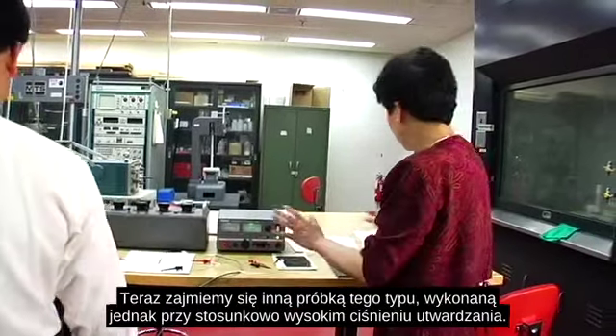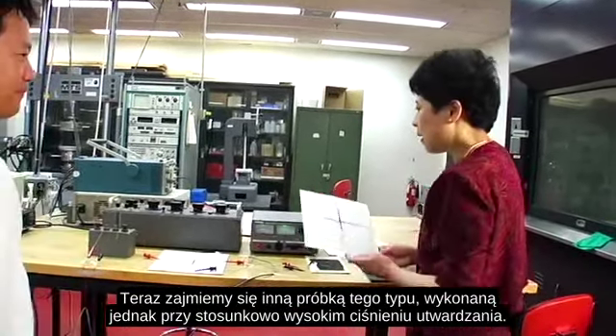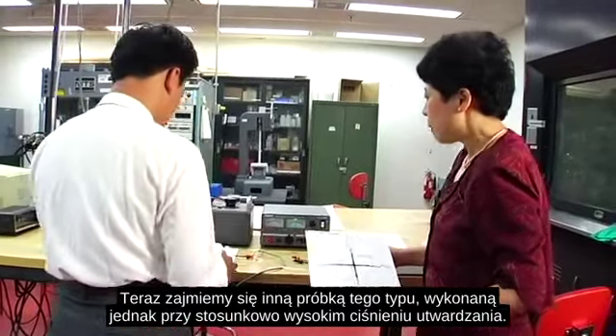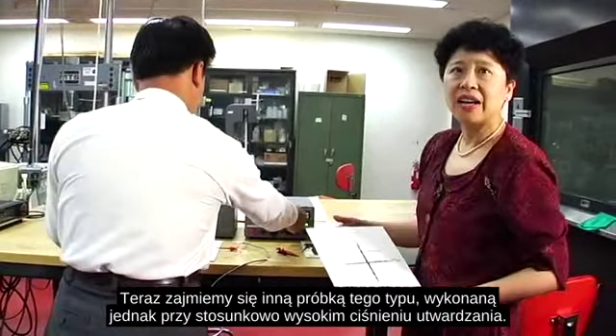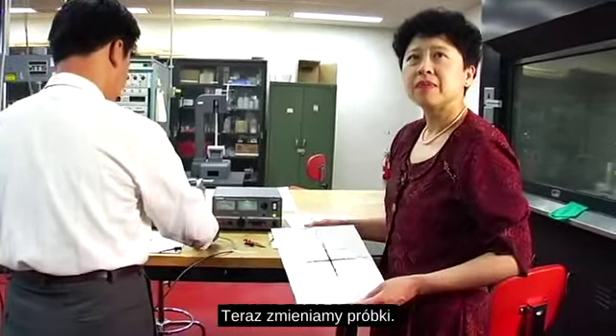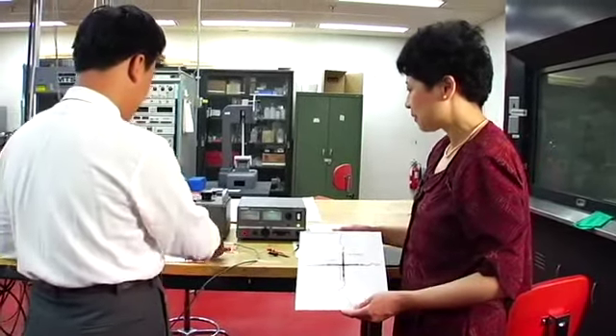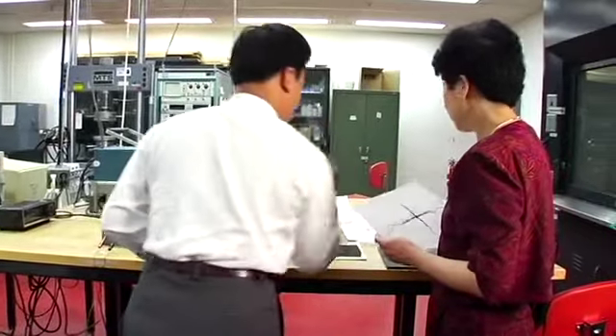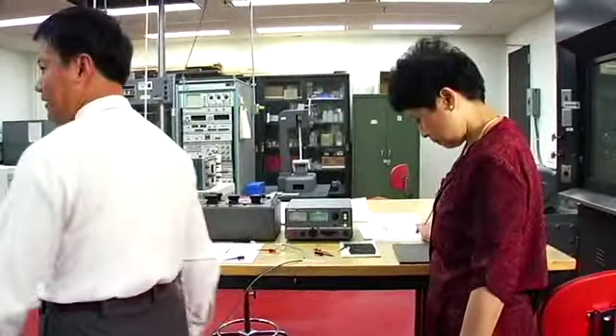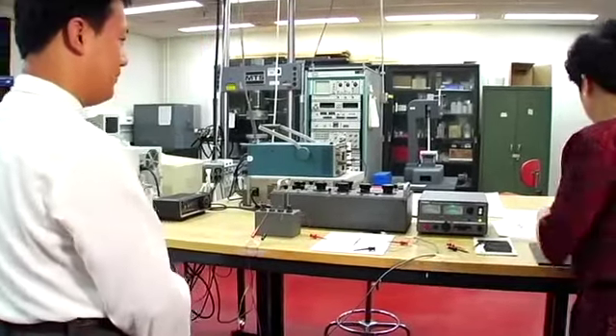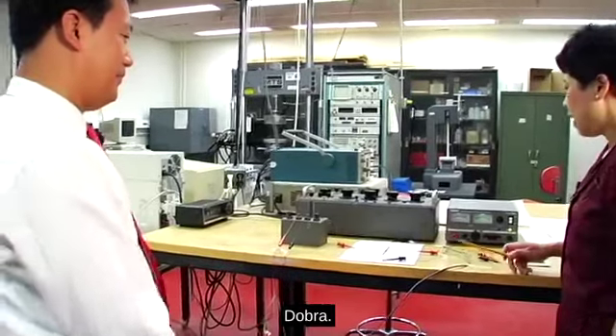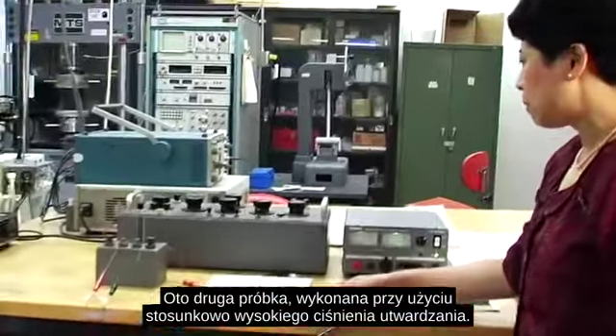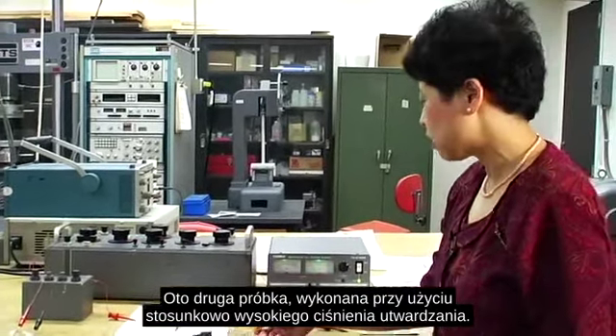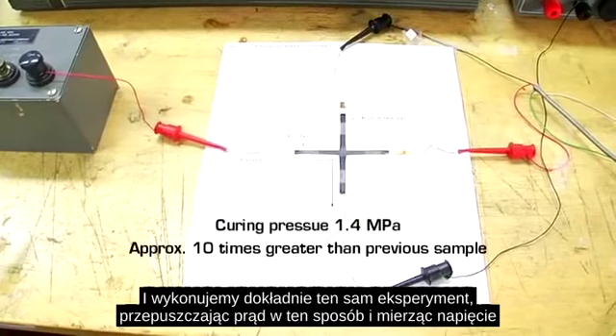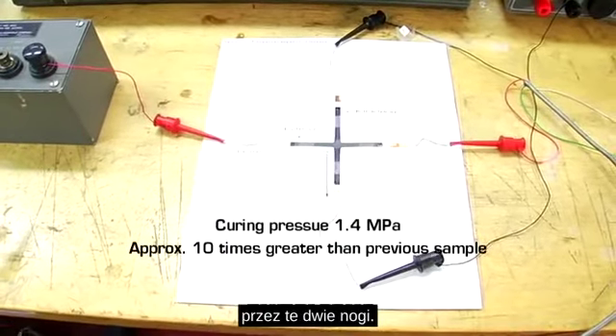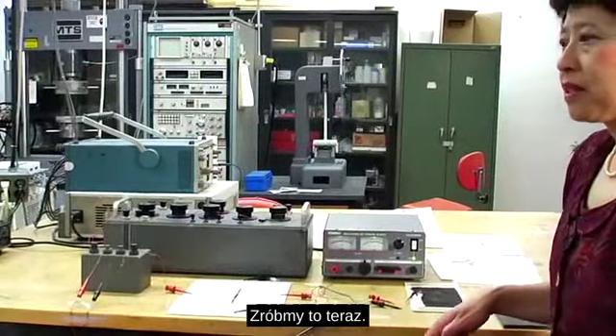All right. So now we proceed to another such sample, but made with a relatively high curing pressure. We're changing samples now. Okay, so this is the second sample, one which was made using the relatively high curing pressure. And we do exactly the same experiment, passing the current like this and measuring the voltage across these two legs. So let's do that now.